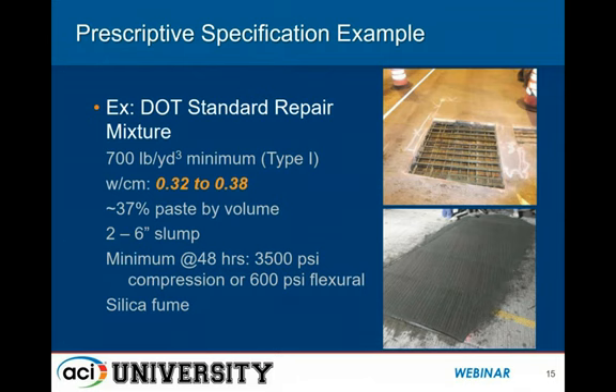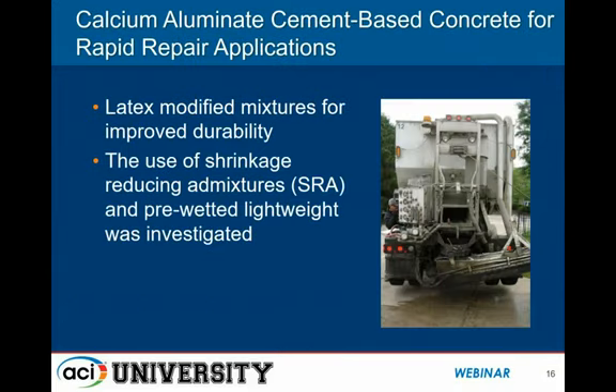What has driven this work, and what I think is critical to the development of a performance-based spec, is that we have existing prescriptive specs, and in many states you have DOTs, for example, that utilize standard repair mixtures, and what you'll find is they're often significantly over-designed for strength, mainly because we're focused on early opening strength and trying to ensure that the opening happens within a very tight time frame, which is usually a consideration that affects traffic, it affects safety. We really don't want to take any risks with having an opening be delayed. So on a prescriptive basis, the mixtures are often significantly over-designed because the focus is really on that early opening. What often comes out of that is then a lack of durability. We have significant cracking issues.